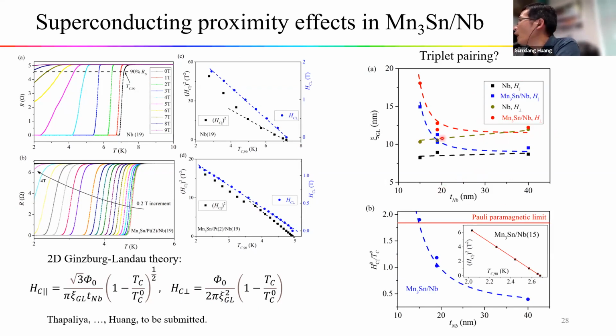For a single layer of niobium, the coherence length slightly decreases as the thickness decreases. However, for the bilayer, the coherence length increases. For the 40 nanometer samples, the coherence length increases by about 50%. So this may be an indication of triplet pairing.